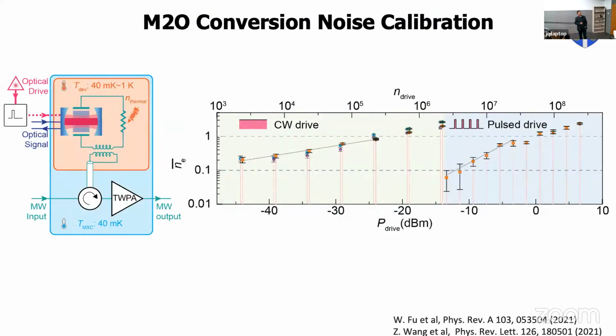and you can demonstrate the microwave to optic conversion. The noise measurement turned out to be a real challenge for us, because when you shine light on the superconductors, that creates a lot of thermal effect, and you also break the Cooper pairs, which could generate noise. We developed quite a few techniques to quantify the noise added by optical photons to the superconductors. In collaboration with my colleague Michel Devoret, his group attached superconducting transmon qubits to our converter and listened to what added noise the superconductor sees. They could quantify the added noise to 0.03 quanta. And there are a lot of ways to do it.